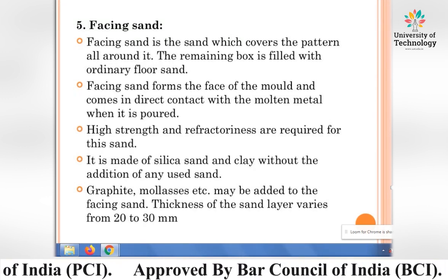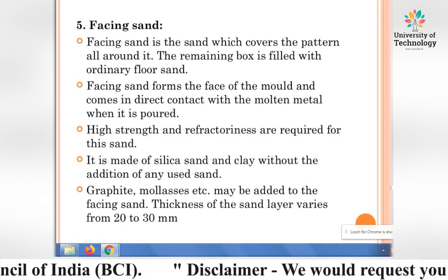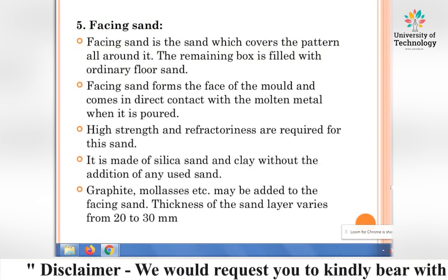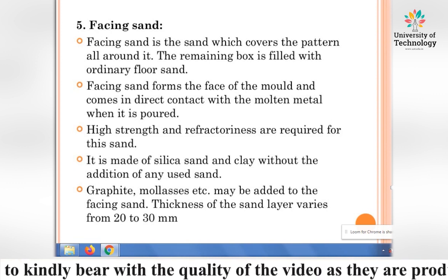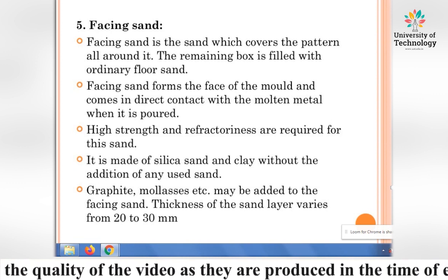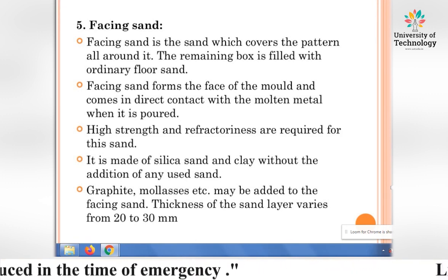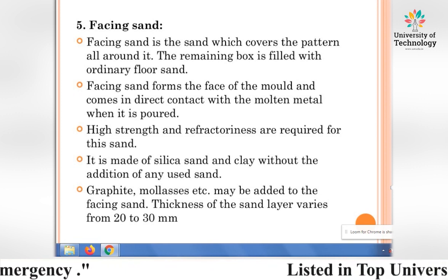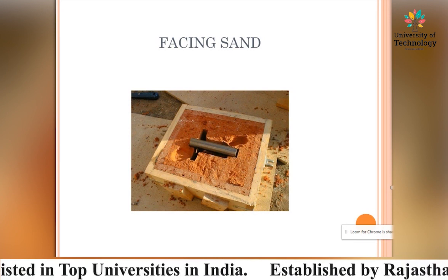It is made of silica sand and clay without the addition of any used sand. Graphite, molasses, etc. may be added to the facing sand. The thickness of the sand layer varies from 20 to 30 millimeters. Here is a picture of the facing sand in this figure.